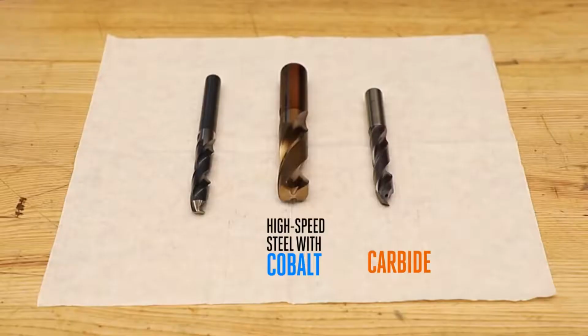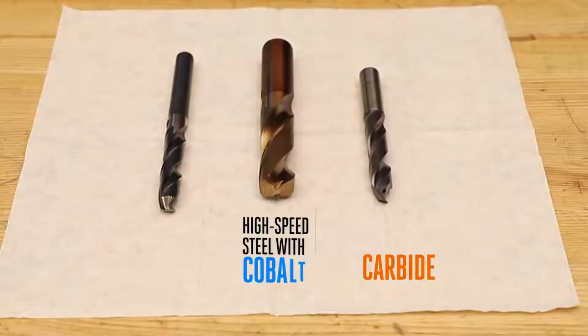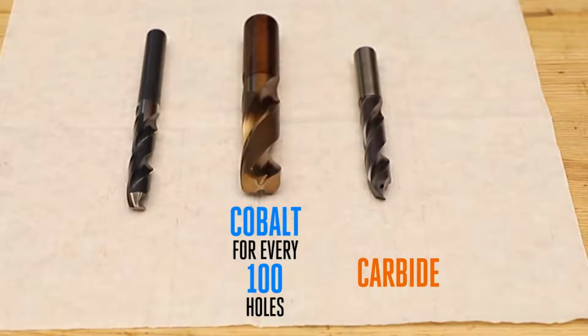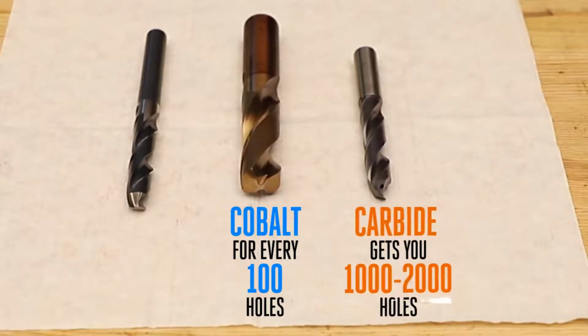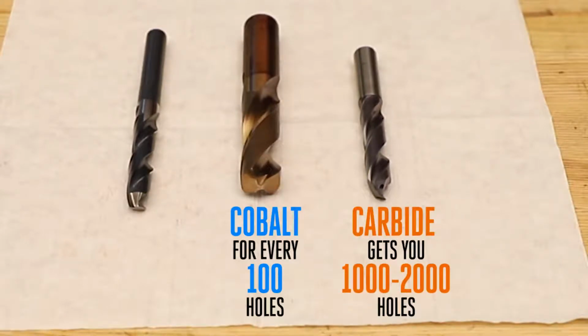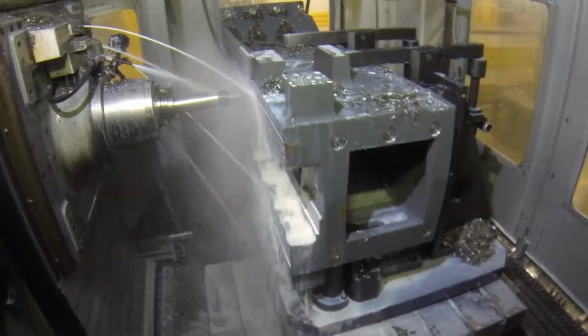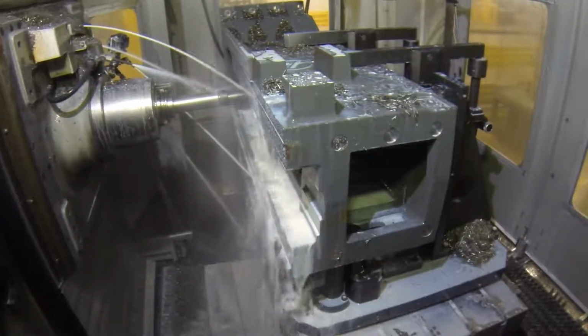While all these drills will cut a hole in most materials, the carbide drills will outlive cobalt by a factor of 10 or 20 times in a rigid CNC machine. In other words, if a cobalt drill will cut 100 holes, the carbide drill will cut 1,000 or 2,000 holes before needing to be resharpened. Here in the factory, with a properly dialed in drilling op, we have examples where we're getting 5,000 plus holes in cast iron from just one drill.